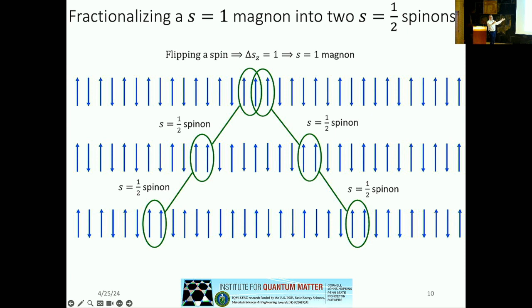It actually splits apart into two domain wall-like entities. So you'll actually see that this domain is different from this domain. This domain is the same as this domain, and it's kind of separated by these what we call spinons. And because this is a spin one particle and I have two of these, then these naturally should be spin half particles. And they actually completely can separate from each other and do not interact. They're asymptotically free degrees of freedom.